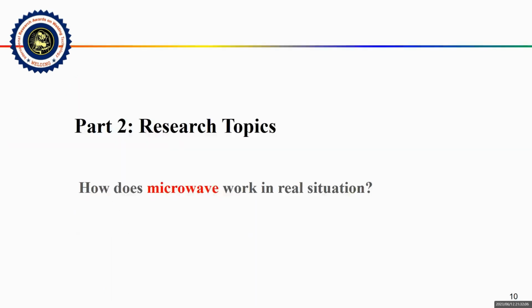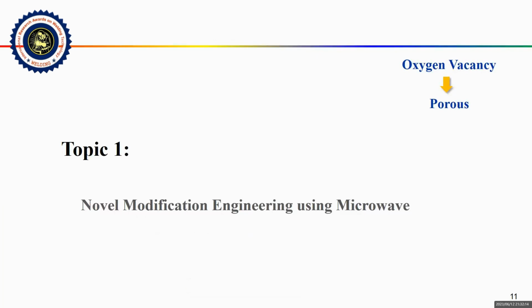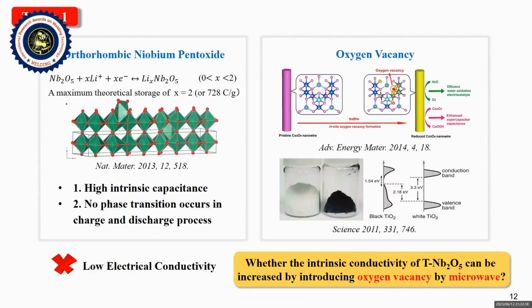So, how does microwave work in our real situation? First, I'd like to talk about the novel modification engineering using microwave. Orthorhombic niobium pentoxide has been widely used as the electromaterial in energy storage due to its high capacitance and no phase transition occurring in the charge and discharge process. However, it has low conductivity. Commonly, the introduction of oxygen vacancy can improve the conductivity of oxides. So we thought whether the conductivity of niobium pentoxide can be increased by introducing oxygen vacancy by microwave.